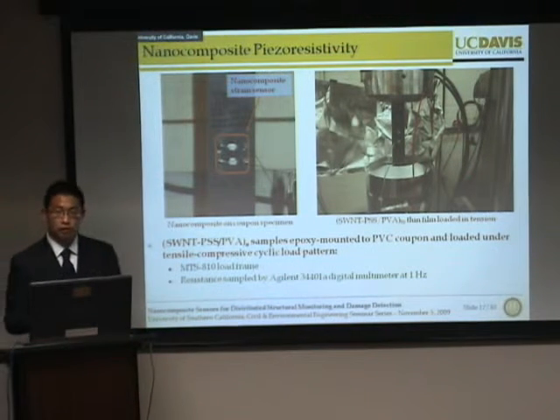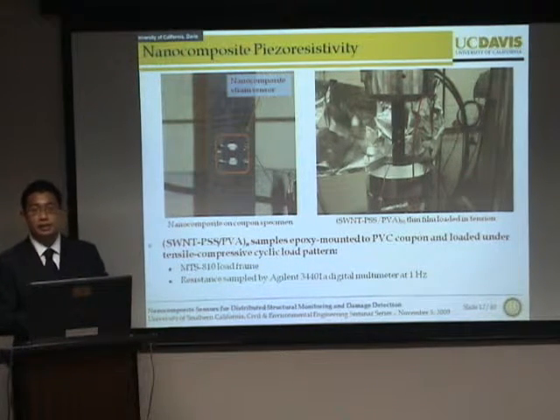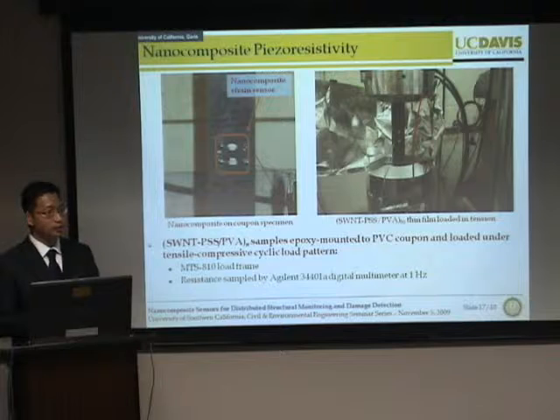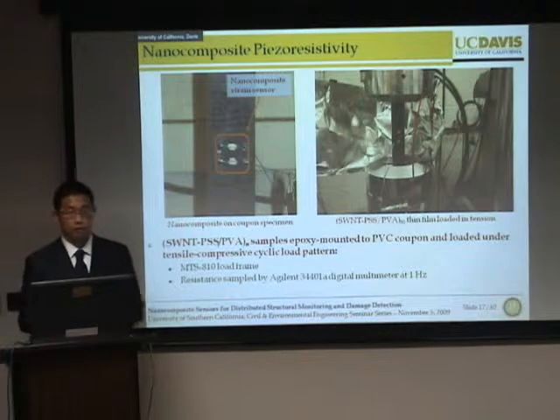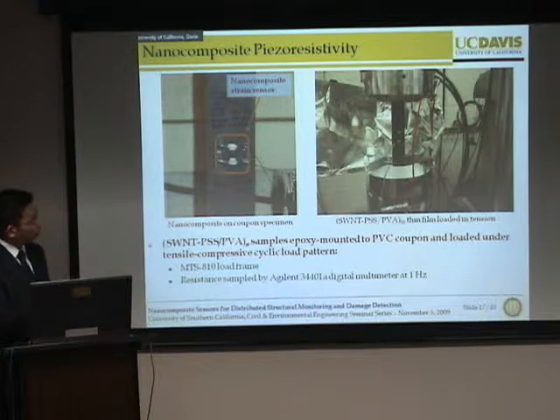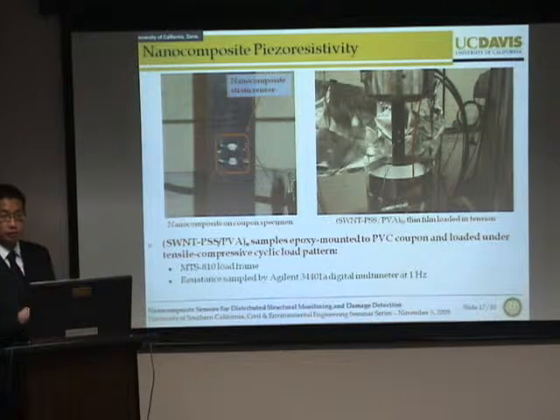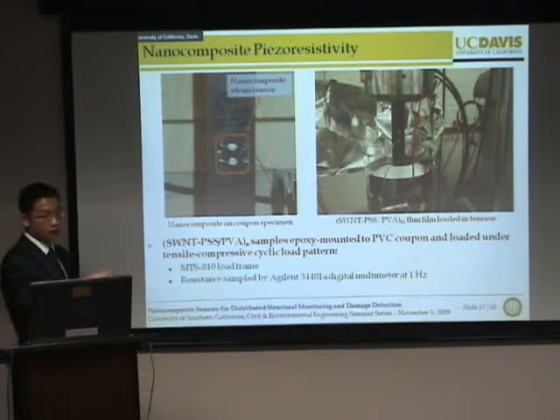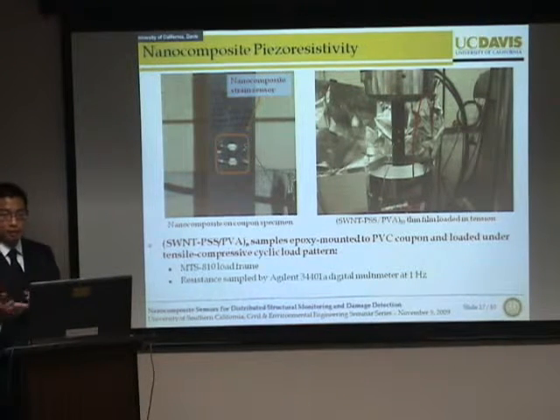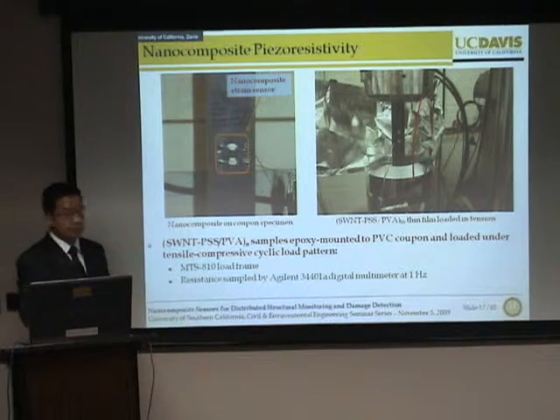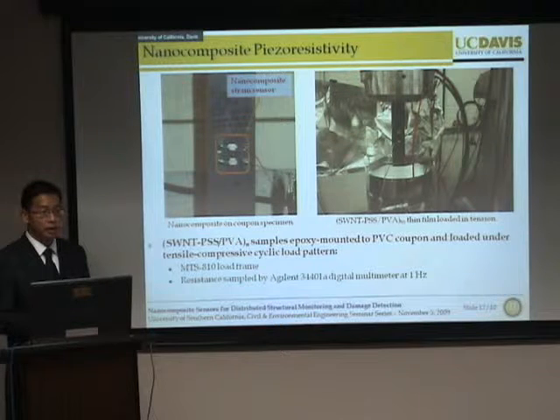So upon running the layer by layer technique, one of the first studies that we want to investigate is the inherent piezoresistive performance or strain sensing performance of this material. So upon thin film fabrication, we then cut a small rectangular piece of this specimen and mounted it on a tensile testing coupon. This specimen is then put in an MTS 810 load frame where we can then apply a tensile compressive cyclic load pattern to it.